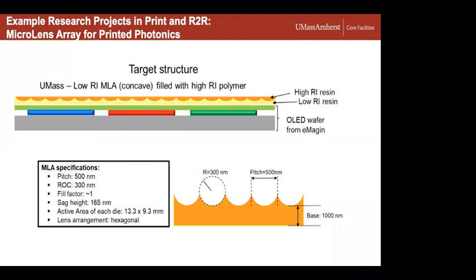This is a project using a microlens array for printed photonics. Again, this is more working in the nanofab and microfab facilities here on campus, creating a nanoimprint lithography mold. This is a specific design where we wanted to create an array of lenses having specific geometries. These are about half micron pitch. Ultimately they wanted an array on the order of a centimeter square, which is pretty much state of the art, getting those types of features over that area. We got up to about 5 millimeters by 5 millimeters.